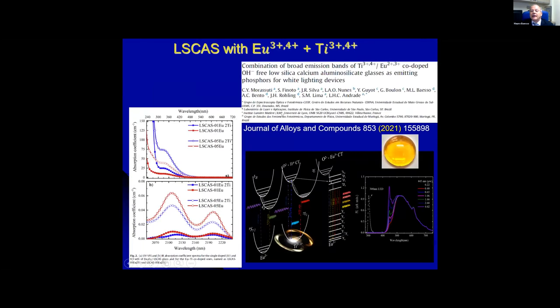We also used a recent paper. This paper is already available online, but it's going to appear next year, 2021. We used titanium and europium. We observe that we can have titanium 3+ and titanium 4+, and europium 2+ and europium 3+ in our glass. We observe that the absorption in the visible is very high, so we can use LEDs to excite the samples and get the emission in the whole visible. That's the idea, to get the whole spectrum and try to simulate the sunshine emission. You see this, this is the color of the glass, it's a very nice color. And also this is the spectral emission from about 400 nanometer to 700 nanometer.